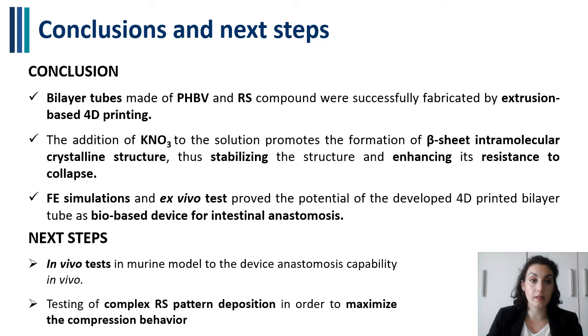To conclude, in this study, bilayer tubes made of PHBV and regenerated silk were successfully fabricated by extrusion-based 4D printing. The addition of potassium nitrate to the solution promotes the formation of beta sheets, thus stabilizing the structure and enhancing its resistance to collapse. Finite element simulation and ex vivo tests were performed and proved the potential of the developed 4D printed bilayer tube as a bio-based device for intestinal anastomosis.